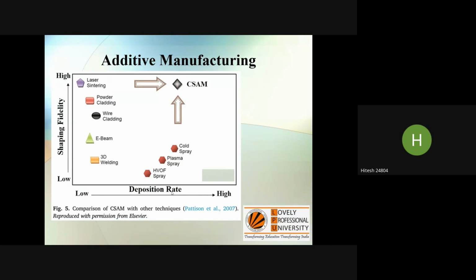with the other techniques, here the deposition rate is very high. Because we are using powder as a material, and we put that material into the powder feeder, and in the nozzles which we are using, the velocity of the powder particles is in the supersonic range. With this very high velocity, we can get metals into action, because it is very difficult to reshape the metal because of its ductility, and the temperature is very low in the case of cold spraying. That is why it is called cold spray, because here the temperature is very low.